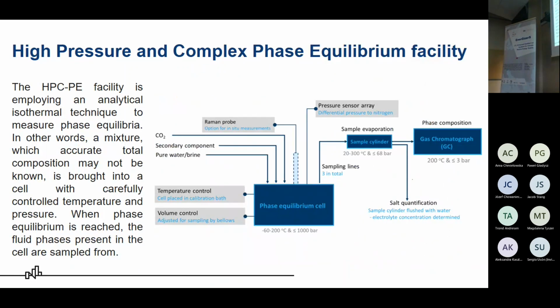In EnerGizerS, a specially designed facility is employed. It is a high pressure and complex phase equilibrium facility. It employs an analytical isothermal technique to measure phase equilibria. In other words, a mixture whose accurate total composition may not be known, but in our case it is known because we prepared 4 mixtures.